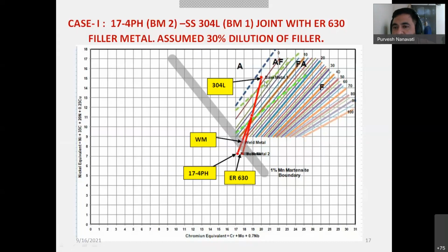Now we will consider an equal mixture or equal contribution from the 304L and 17-4 PH, right? The equal contribution, 50% from this one, 50% from this one. Now ER630 filler metal will come somewhere here. Their composition will come somewhere over here. Now we will connect this point with the middle of this line, right? This lead line. So what will happen depending on the dilution? Say it is a 30% dilution, or a 40% dilution, or a 60% dilution of the filler metal.